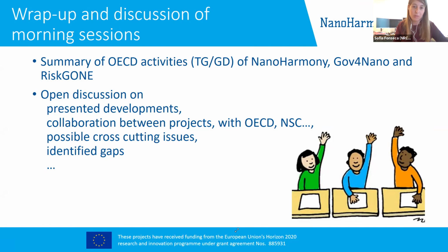The need for creating these new standards applicable for nano was because the previous standards, the CEN standards for conventional materials, did not seem sufficient, so they could not address the nanomaterials as such. They were not considering the number concentration and the number size distribution, which we believe are crucial to be considered in these methodologies, so it can properly describe the behavior of the material in the air and also its intrinsic characteristics. On top of these requirements, some of the previous methods developed for dustiness required quite big amounts of mass being introduced. So some of these methods were optimized, and now they require lower quantities for safer and cheaper purposes.